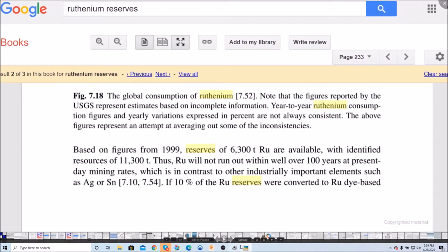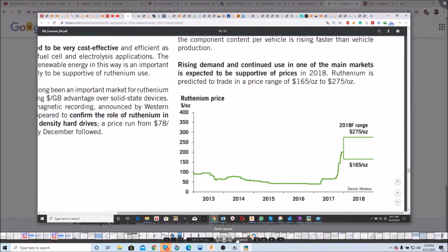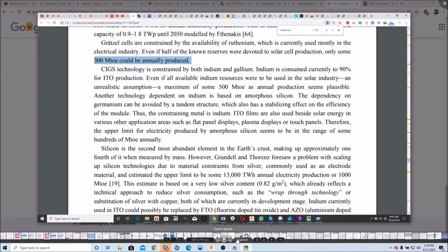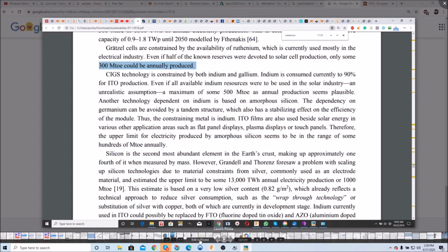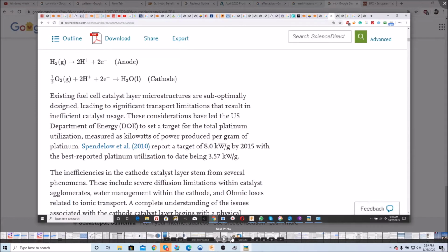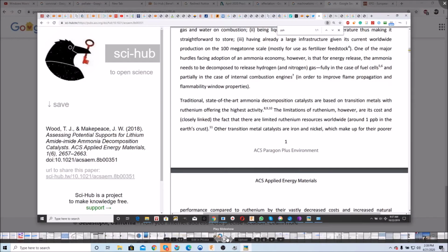11,300 tons of ruthenium reserves. The reason I brought up the ruthenium reserves is because if you read papers about ammonia decomposition, a lot of papers are studying alternative, non-noble catalysts, and they're citing the short supply of ruthenium as a potential barrier to implementing a widespread ammonia economy. For that reason, since it's considered a viable potential large-scale energy system, we need to ensure that supplies are sufficient, but they are. It's not a limiting factor.